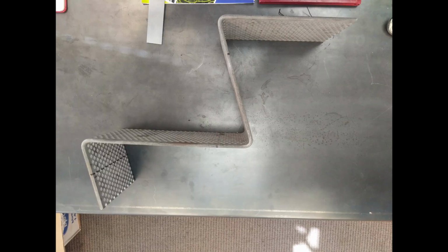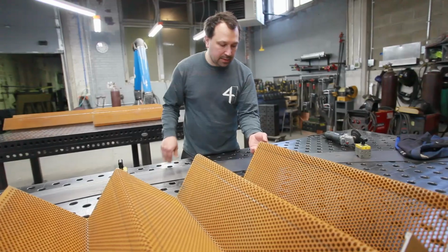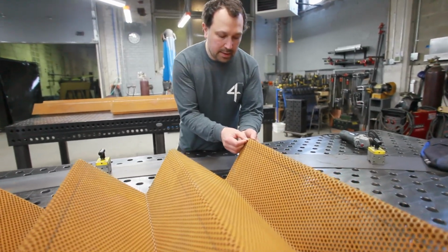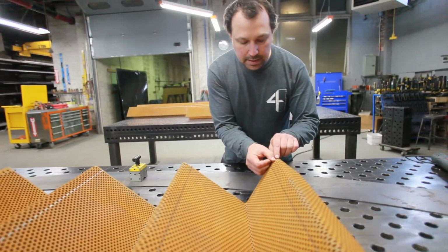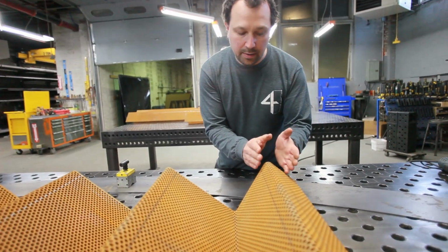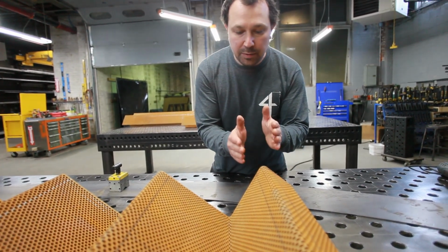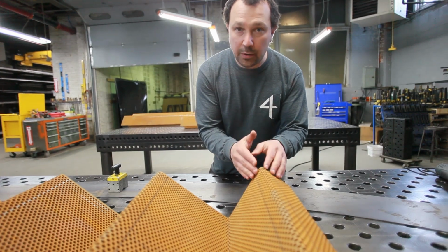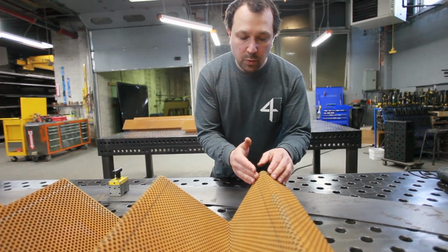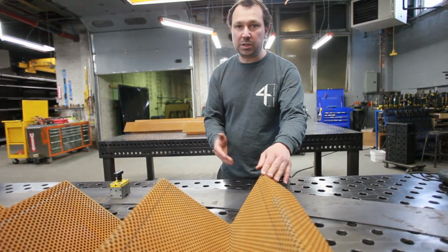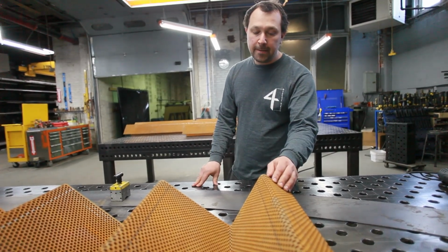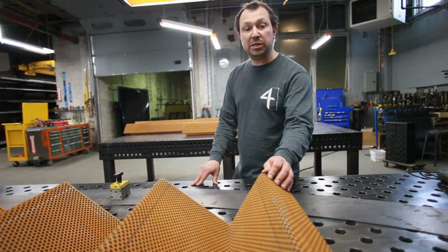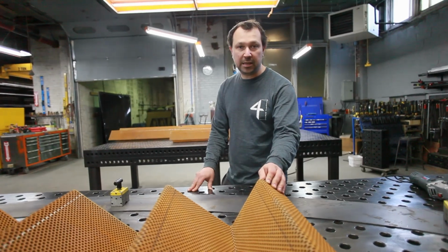The other problem we had with the factory material is that when we bent it, the location of the bend shifted because the material wants to bend in between these 2 holes somewhere. We found that the material would slip as it was going in and thus would not bend where we wanted it to, which was a big problem for this. Luckily, when we got the annealed material back, that seemed not to be an issue anymore.